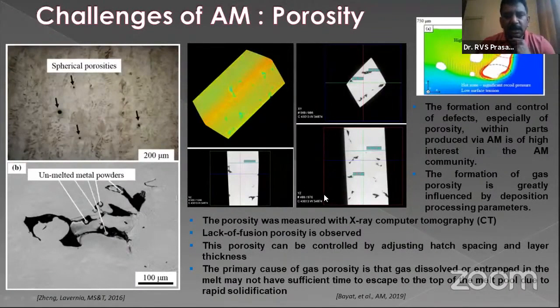When it comes to defects in this particular field, you have a lot of challenges like porosity, which is very common in 3D printing. There are two different types of porosities. One is process induced porosity, which occurs during the process or melting, and then there is powder induced porosity, where the input material powder itself may have porosity from the atomization process. So these two porosities will be different. The selection of powder and characterization of powder is very critical before feeding the powder into the 3D printing machine. So initial qualification and certification of the powder is a very important aspect. At the same time, process induced porosity.